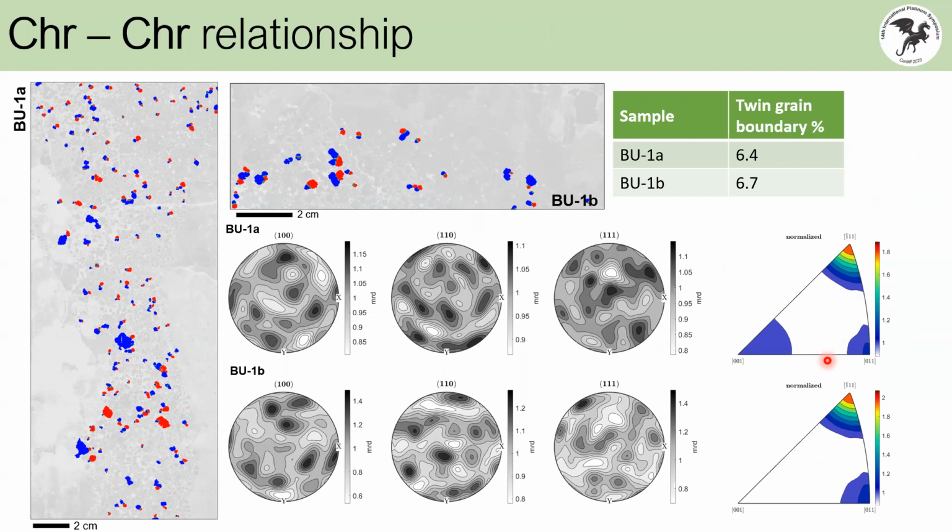For other oxides it will be different and more difficult. For example, in magnetites it's impossible to say anything about primary structure because they're completely recrystallized. They change the grain shape. In chromites, when they're enclosed with the interstitial phases, it preserves the primary structure. So you mean the chromite in UG2 is also recrystallized?